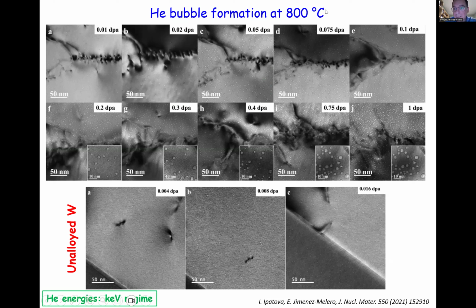And we did this at 800 degrees, and we wanted to understand how those helium bubbles form in those materials. You have to think that for transmission electron microscopy, the TEM sample or lamella is very thin. It's around 100 nanometers in the area that you are analyzing. But you can see as you increase the dpa, you increase the damage or the fluence, how you start to form all these white dots, which are all these helium bubbles, and they start to accumulate and grow. And you can look at the very earliest stages of that formation.